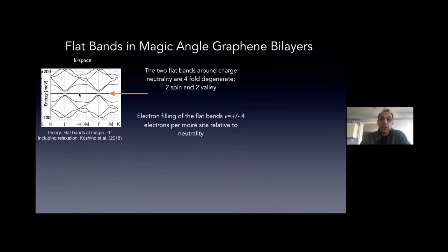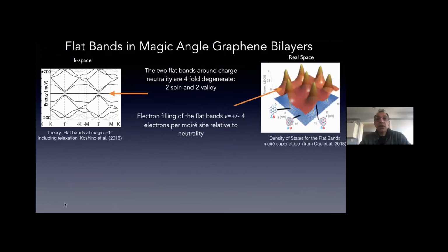So let me just orient you. These are things that Dimitri already pointed out. By twisting the angle to the magic angle in bilayers of graphene, you get two very flat bands separated out. This was predicted theoretically by Allan MacDonald and others. And immediately, of course, when we have flat bands, you can think about what you have in real space. In real space, from this single particle picture, you get the local density of states where electrons are living, having this enhanced density of states at these Moiré superlattice sites.